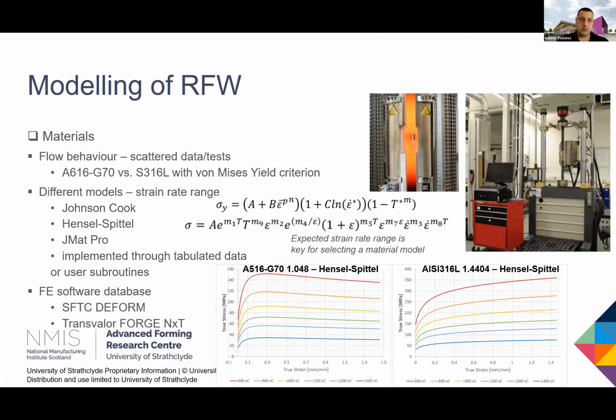Quite a lot of discussion around material properties. We had some scattered data published and available online. We used those, but we did not get very good results. There are a number of different models. My personal preference is to try and use those models that correspond to the strain rate range that we are expecting. Johnson-Cook models typically are used for high-speed machining. I'm not so keen on those. I prefer the Hensel-Spittel models because they are mostly relevant to those kinds of conditions.